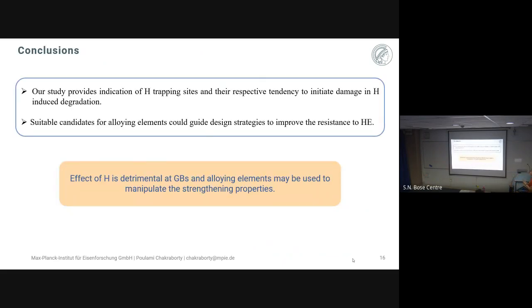Therefore, our study provides indication of how we can increase such hydrogen trapping sites, which are the solute elements which can increase hydrogen trapping sites, and which are the elements which need to be avoided, and their respective tendency to initiate damage in hydrogen-induced degradation. So this can also lead to suitable candidates and a materials design mechanism to improve the resistance to hydrogen embrittlement, and that is the most important, and that makes it most significant.